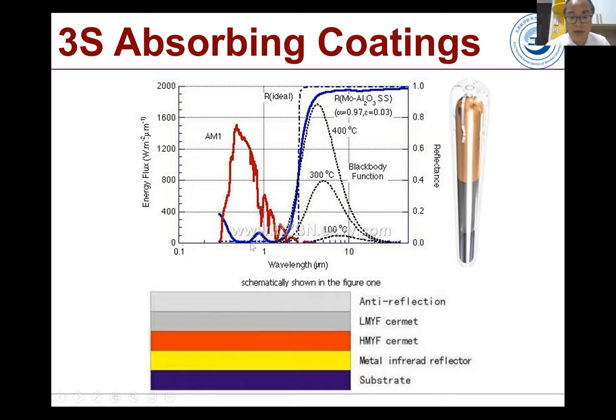So this is the blue line in the figure. Here is still the solar sunshine radiation part. And the blue line is an experimental result of the reflectance of this coating's layers. You see within the total solar region, the reflectance is almost zero. That means the absorptance is very high, as high as, you see here, 97%. But in the far infrared, its reflectance is very high.